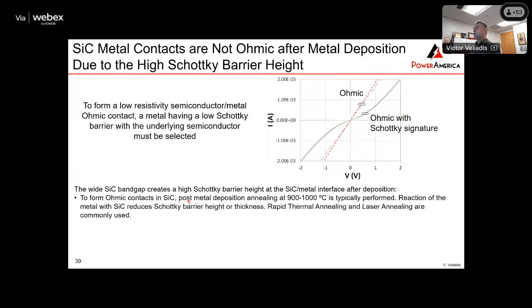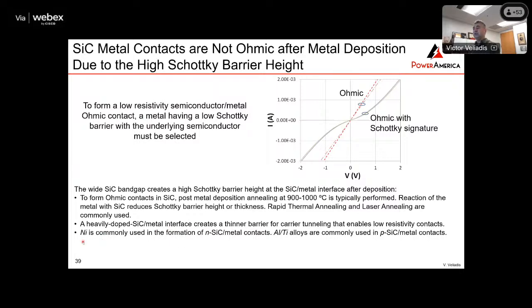So to form a low resistivity semiconductor metal ohmic contact in silicon carbide, you need to basically follow some steps. You need to put down the metal and then anneal at 900 to 1000 degrees. And you can do that either in a rapid thermal annealer or you can do that with a laser annealer. And you need a very heavily doped silicon carbide surface at the place where you're going to form your ohmic contacts. And nickel is commonly used to form N-type silicon carbide metal contacts. And for the P-type metal contacts, the best one is the aluminum titanium alloy.